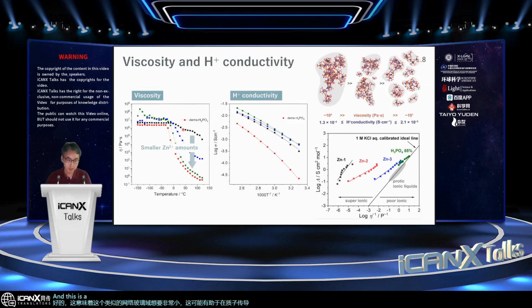And this is one of the results of changing the amount of zinc ion used. So simply said, if we reduce the amount of reacting zinc, viscosity goes lower because more fragmentation occurs. So it's going to behave more like the liquid state. Which means we can control the mechanical properties for the electronic device. But in this case, the good thing is that the proton conductivity is quite high regardless of the amount of zinc used, like this.